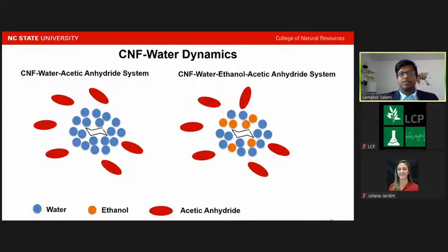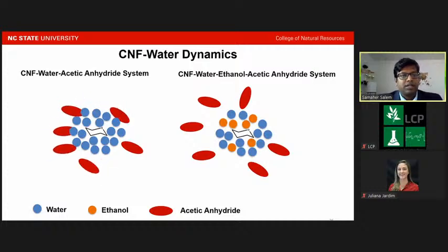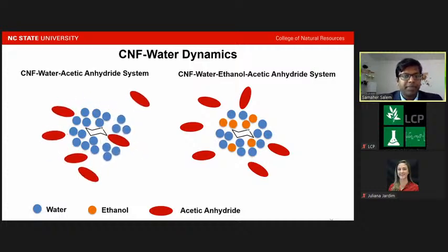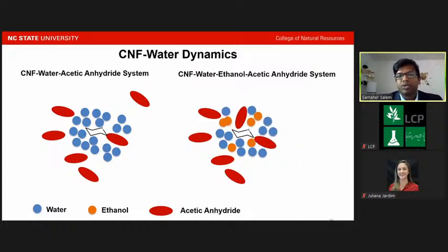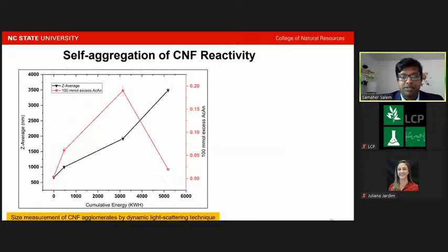This is a schematic representation of the CNF-water dynamics, and we could see that for the water and acetic anhydride system, the hydration shell is much, much stronger. And thus, only a small amount of acetic anhydride molecules could penetrate and reach the surface for reaction. However, for the water-ethanol system, the hydration shell was not as strong as in the water-only system, and thus more cellulose nanofibrils could interact with the acetic anhydride, and thus the reactivity increased.